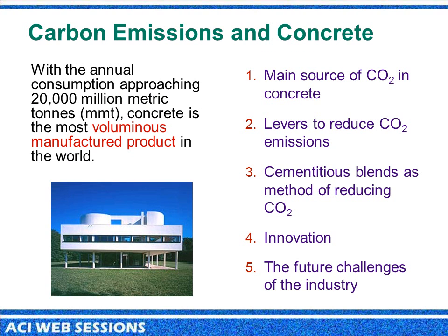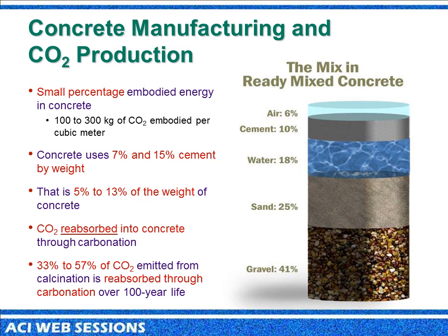When we look at concrete today, the one thing we're most notorious for is cement production, and cement production is obviously the key trigger for CO2. But there are levers to reduce CO2 in concrete mixtures, primarily using blends of supplemental cementitious materials, or also looking at innovation, but with those come challenges. When we look at concrete manufacture and production, concrete itself has a very small embodied energy. And typically cement is only a very small portion when we take into consideration the other materials used in concrete mixtures. CO2 can be reabsorbed into concrete, but that's primarily after it's been crushed.